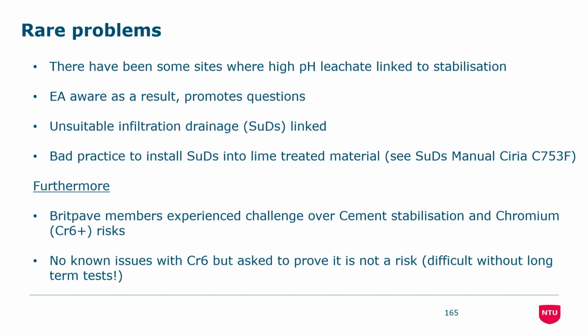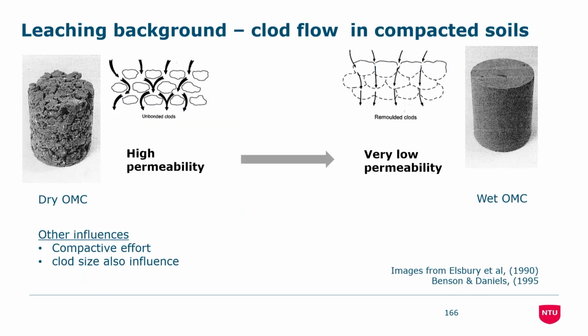We then also became aware of BritPave members being challenged over the use of cement stabilisation, and particularly the challenge that was put forward on a site was the question: can you prove that it won't be a chromium-6 problem? Will you get chromium-6 leaching into an aquifer or a watercourse? Chromium-6 is cancerous. There's no real specific reason why that would happen, because the cement industry has gone to a lot of effort to introduce processes to put iron oxide into their cement so that when it hydrates, the chromium-3 remains non-oxidised, in a lower oxidation state, so it would not be the cancerous or bad form, chromium-6. So there's no reason to think why stabilisation would suddenly cause that, but that was the logic, and if there wasn't a strong and robust case to say that wouldn't happen, then you can just be refused permission to go forward, and indeed in those examples that's what happened.